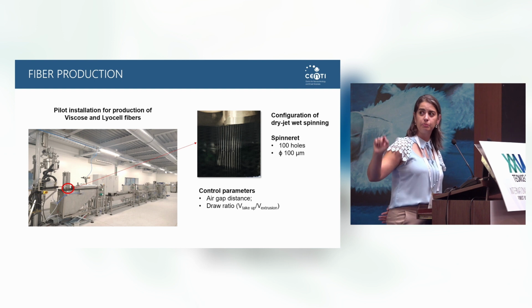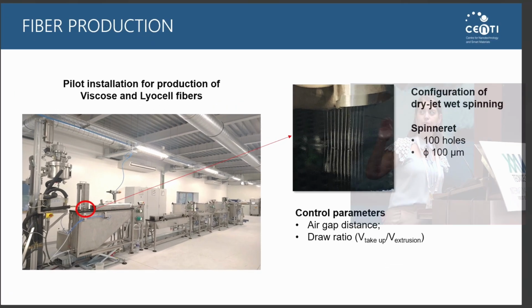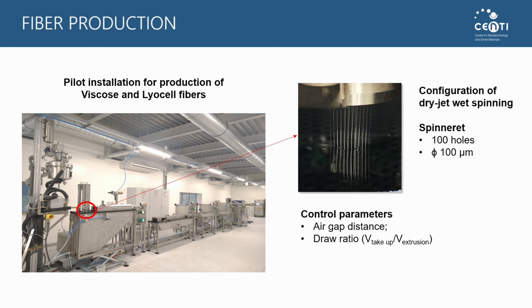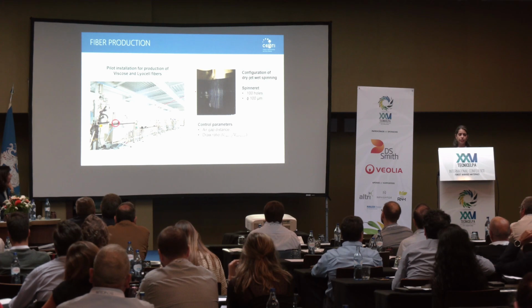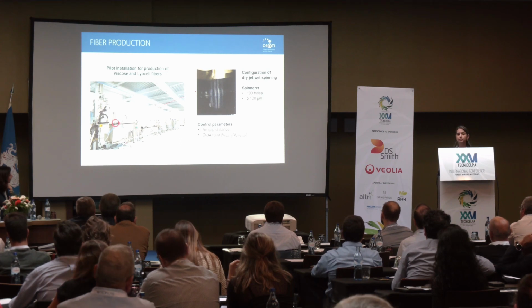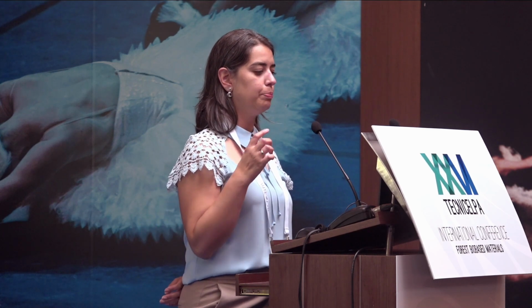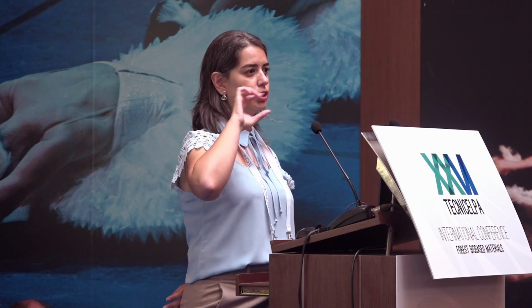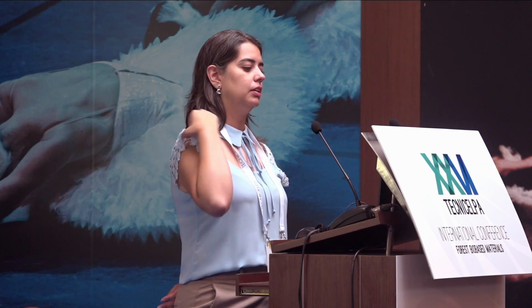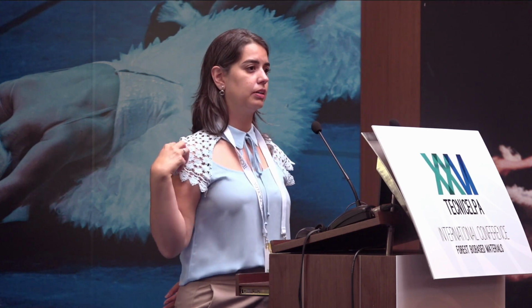After this first bath is the coagulation bath, and after that we have the washing baths, dryer, and winder. For the lyocell process, as the dope needs to be heated during spinning to lower its viscosity, we work in a configuration of dry jet wet spinning. That means the spinneret is outside of the bath, creating an air gap on top of the solution where the fibers are created.